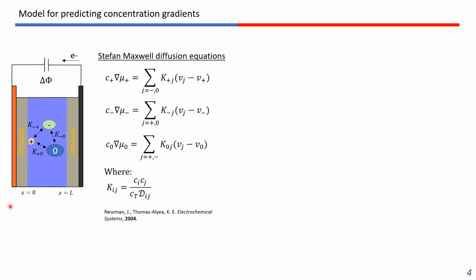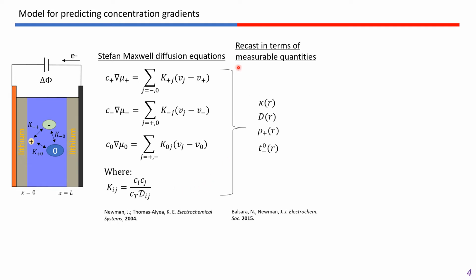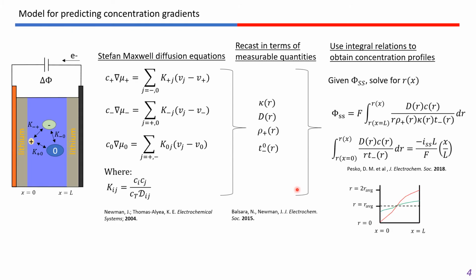So to begin to answer these questions, we first want to consider the magnitude of the salt concentration gradients which form. And to do this, we can apply Newman's concentrated solution theory, which starts with the Stefan-Maxwell diffusion equations applied to a concentrated liquid electrolyte. From here, we can recast these equations into measurable quantities and then further derive these integral relationships, which can yield the cell concentration profile as a function of position in the cell when these four transport parameters are known as a function of salt concentration.